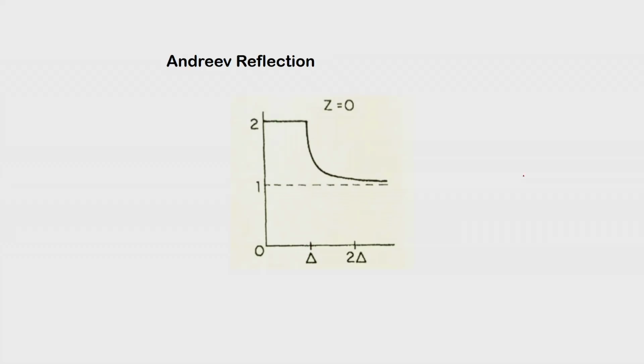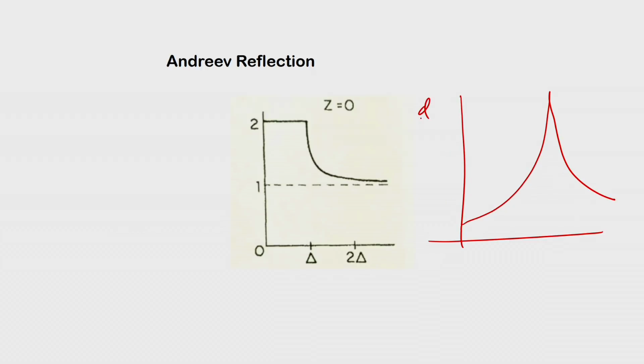So, this edge would determine that the delta is there, and if I take a differential conductance, then it will show that there is a peak there. Okay. So, this is I versus V, whereas the dI/dV versus V would show a peak, where there is a discontinuity, and this will be the position of delta or the energy gap. So, these are some of the experiments. This list is of course not exhaustive. There are many other experiments, but one needs to understand at least a few of how experimentally one determines the gap.